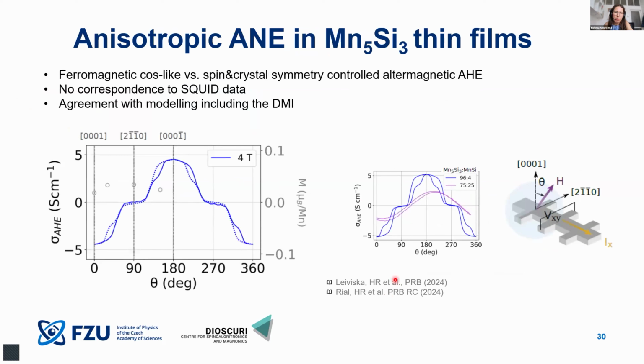So this is already a good hint that the anomalous Hall effect here comes from the altermagnetic origin. And further evidence is that, unlike in ferromagnets, we expect a very particular anisotropy of the anomalous Hall effect in altermagnets, because it relies on the combined spin and crystal symmetry and their mutual orientation. When we control the spin with the external magnetic field, we also change the respective orientation with respect to the crystal. And therefore, we will have some plateaus where the anomalous Hall effect is basically not allowed. And this is more or less exactly what we observed.